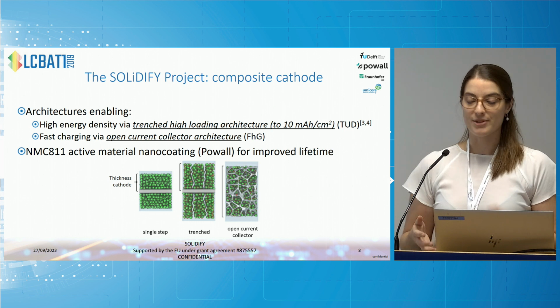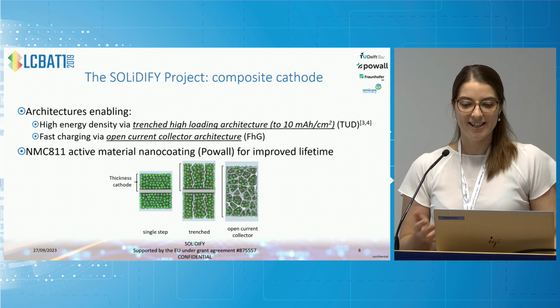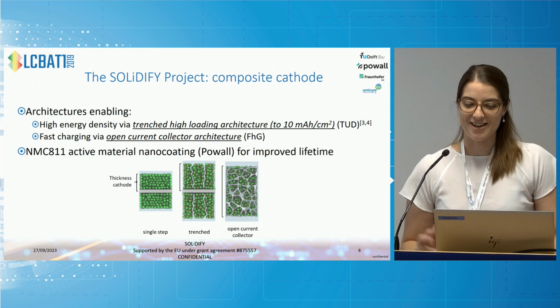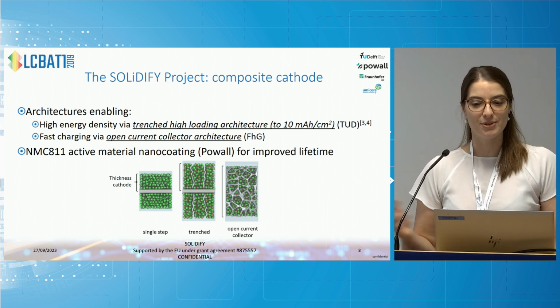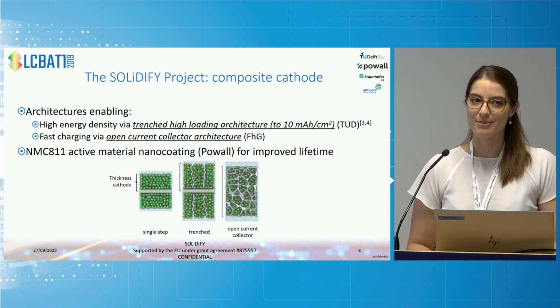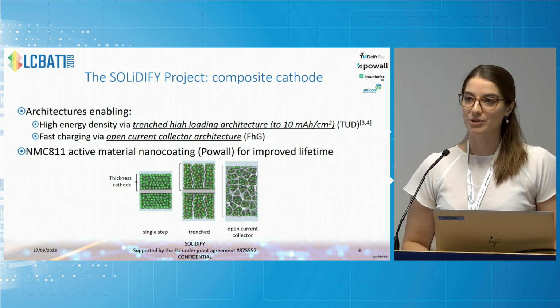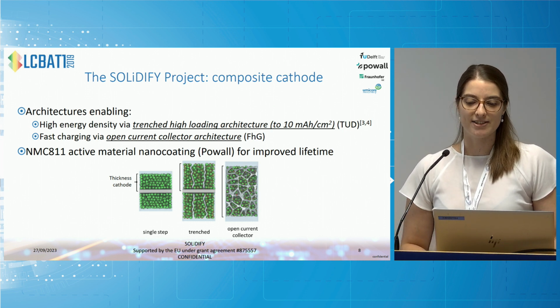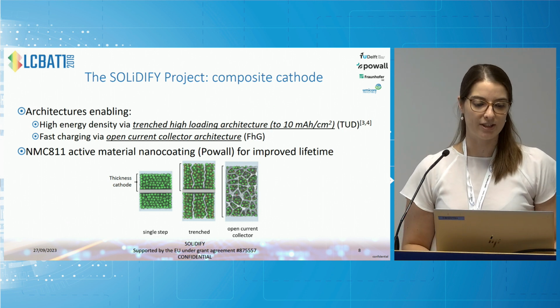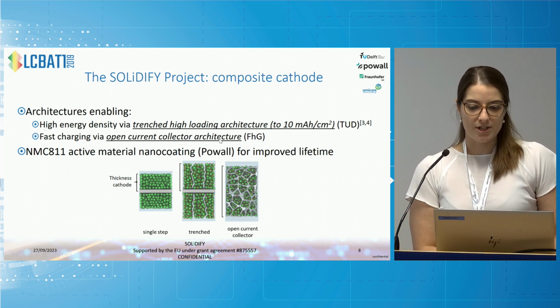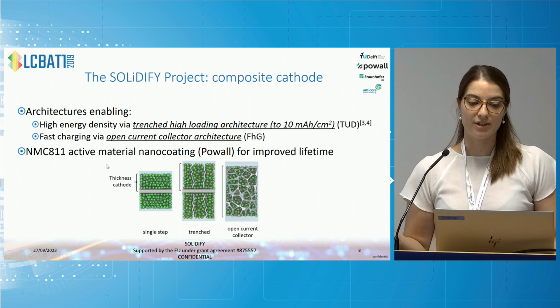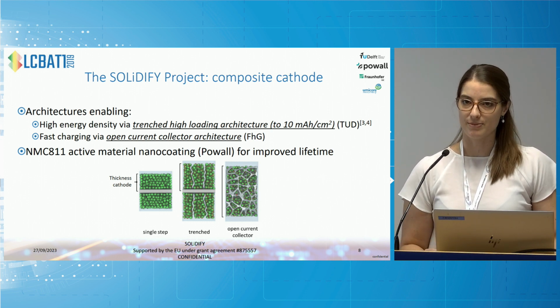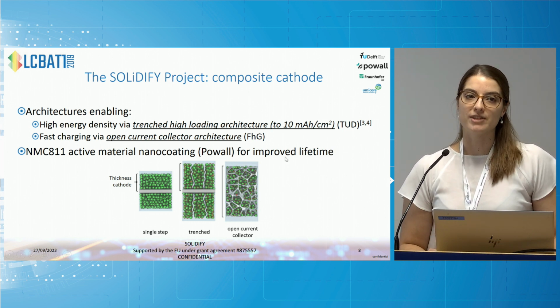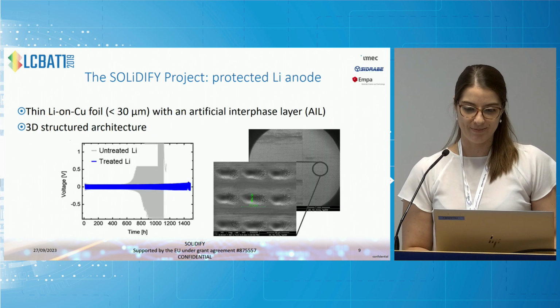And we are, similar to previous projects just presented, looking at quite high loadings, very high loadings, I'd say up to 10 to 12 milliamp hour per square centimeter. There are challenges, of course, that have already been highlighted with using high loadings, but that's the intention and what we're working on right now. And in collaboration with a partner, Powall, they produce nano coatings on the active material, the particles themselves, before the cathode is assembled. And this predominantly is for improved lifetime and cyclability of the cells.